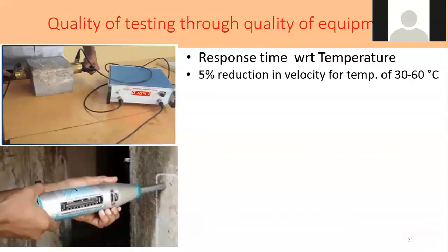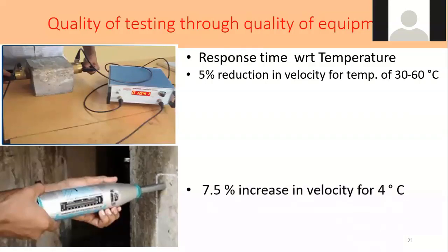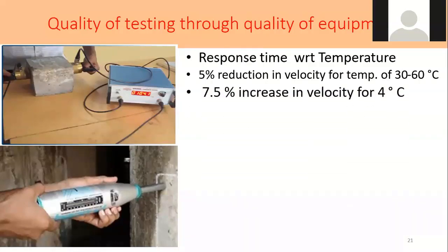Next, please. When the temperature outside in the field is in the range of 30 to 60, next please, then we need to apply a correction. A 5% reduction in velocity is to be considered when the temperature outside is very high. It is the other way around if the temperature outside is low, to the tune of 4 degrees centigrade, then a 7.5% increase in velocity is required to be maintained.